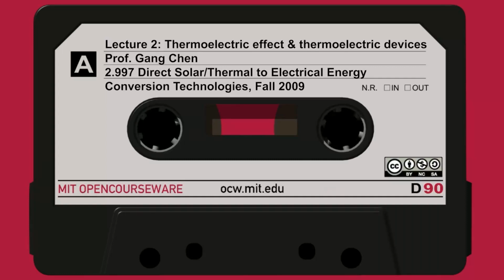And then you look at this function, you want to maximize your ZT to get a higher efficiency. So the first thing is that you go to maximize your Z by geometry. You can reduce the denominator by changing your L over A, right? That's the least you can do if you don't work on the material. And that's what you want to minimize. And if you minimize it, it turns out this is what you have to do. The K times R, this is the minimum when you match the length and cross-section area of the two legs. So as an engineer, this is where, when you build the device, you optimize it. And when we do that testing in our own lab, sometimes it just involves hand polishing all this, trying to make it match to each other. So you want to get a better performance than others, right?